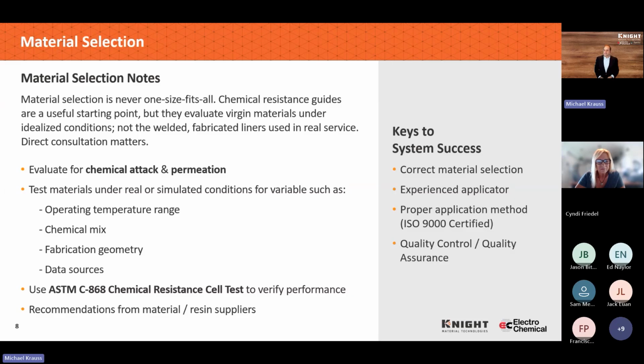What I would say is, in my 30 years of experience, I have yet to see an application that made a difference on PVDF, whether it was emulsion or suspension polymerization, in terms of how it's made. The end product ends up being roughly the same. The rheology might be a little bit different, so trying to mold two compatible grades, you might get a slightly different shape or size. But if you make a sheet of 1/2-inch PVDF, whether it's emulsion or suspension polymerization, the mechanical properties and chemical resistance are going to be identical.